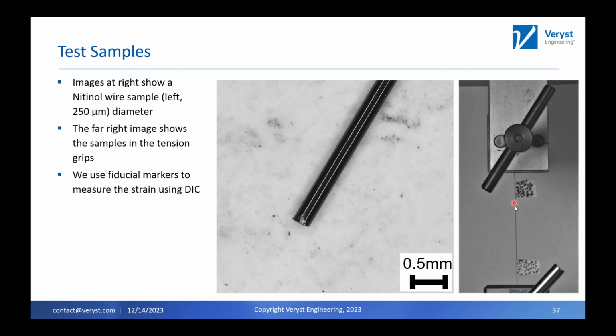So it's that same 250 micron wire. We're using just screw grips here. We've clamped it in between there. And then in this case, to measure strain, what we do is we add fiducial markers. That's what these are. So we track these with those same video cameras to measure the strain in between here.